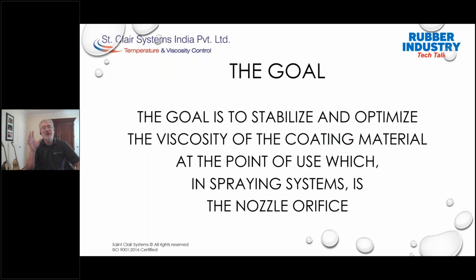So our goal must be to stabilize and optimize the viscosity of the coating material at the point of use, which in spraying systems is the nozzle orifice. Now, in order to get a predictable film repeatedly, no other material temperature in the system matters as much to the outcome of the coating process. So how do we manage that?